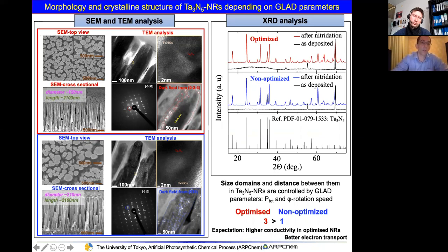What we can see here in the red square and the blue square: this is the optimized material and this is the non-optimized material. If we compare optimized and non-optimized material from the XRD analysis, there is almost no difference, very similar. However, if we look deeper from the TEM analysis, especially from the dark field, we can say that both materials are polycrystalline. And from the dark field, we can see the domain size. The domain size is about 3 times higher in the optimized material in comparison to the non-optimized material. Thus we expect higher conductivity in the optimized nanorod and better electron transport.